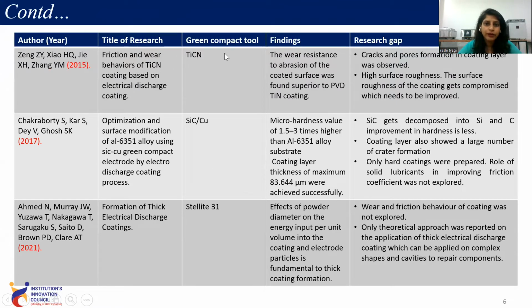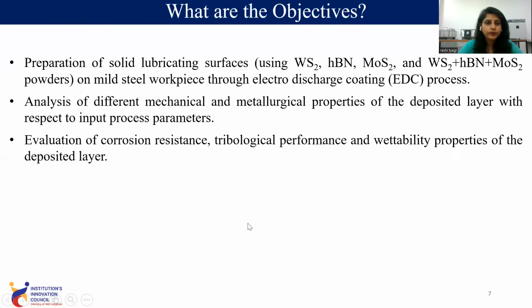In this, titanium carbonitride, silicon carbide, copper, and stellite can be used. So these are the findings of the research gap, and there is a research gap in which we have found that there are cracks and pores formation. Cracks and pore formation are there. Also, some of the research does not discuss the wear and friction behavior of the coating.